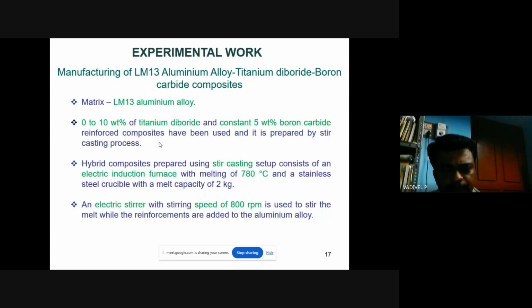The hybrid composites are prepared using a stir casting setup consisting of an electrical induction furnace with a melting capacity of 780 degrees Celsius, and a stainless steel crucible with a melt capacity of 2 kg. The aluminum metal is melted by using the electrical induction furnace. The capacity of this induction furnace is nearly 1500 degrees Celsius. Here we have chosen a temperature of 780. The aluminum is melted and kept for 0 to 5 minutes in the furnace, and then it is stirred using the electric stirrer with a stirring speed of 800 rpm. The optimum range of this electric stirrer speed we have selected by using various experiments.